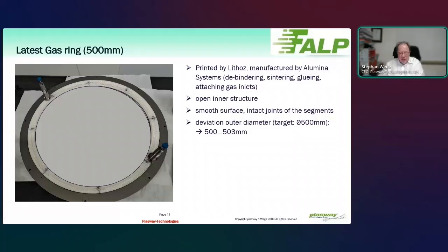Then we got nice support from a company that is already interested in a 17-inch reactor, not just 300 millimeters. So we had the challenge that we now need a ring with an inner diameter of the order of 500 millimeter. Alumina Systems will later explain how we did it. You see it is made out of parts, but we have again the same system with the gas nozzles, so that each second nozzle brings in precursor A and the other brings precursor B.